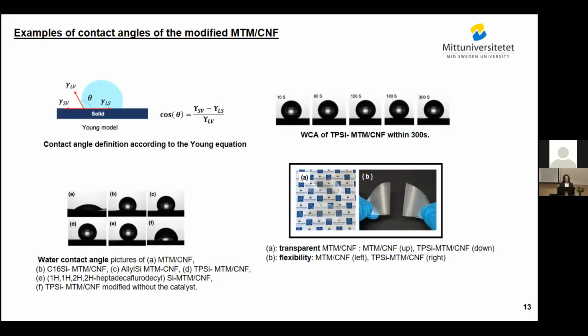Also here I tried to show the durability and the stability of the surface when the water has contact with the surface. I measured until 5 minutes, and all the data that I reported is at 5 minutes. I wanted to see the transparency and also the flexibility, if it changed, but it looks like after modification, we don't have a big change in the flexibility compared with before modification, and in transparency.